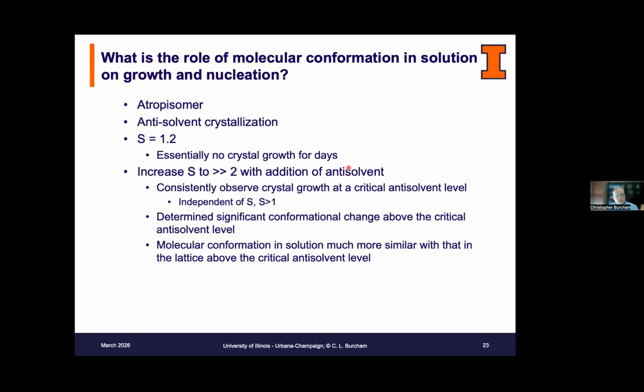In fact, as we increased the supersaturation ratio to an excess of 2, we still saw no growth at all until we got to a critical anti-solvent level where we started to see growth. And it wasn't nucleation, it was just growth. And the question is, why did we see this change? And it was very repeatable. Once we got to that critical anti-solvent level, independent of our level of supersaturation, growth would happen.